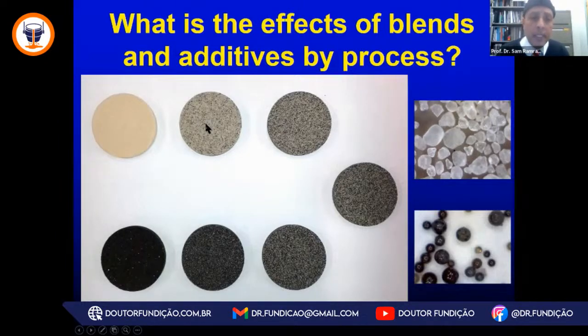We could have it where it's 80% silica sand, 20% the ceramic, or vice versa, 80% ceramic, 20% silica, or 60-40, 40-60, as the case may be, to study what are the thermal benefits, such as heat transfer, mechanical strength, or any dynamic properties. They all change with blends. But the issue is that the foundries are doing this primarily to reduce their sand to metal ratio to save money, and also to lighten the weight of the cope for large size castings. Why? Because the bulk densities of the natural aggregate like silica sand is significantly different from our alternative ceramic sands.